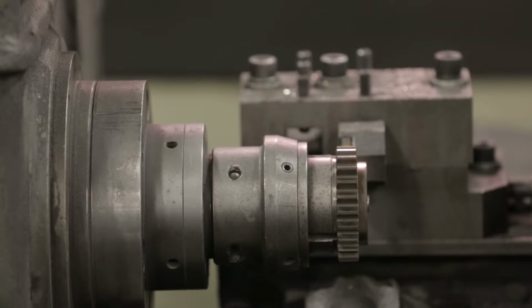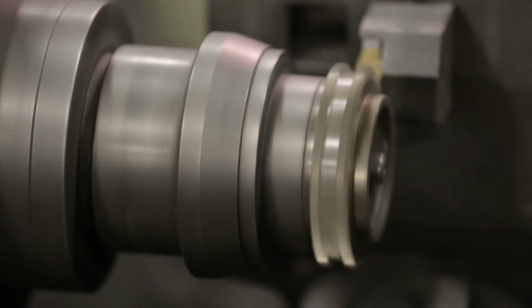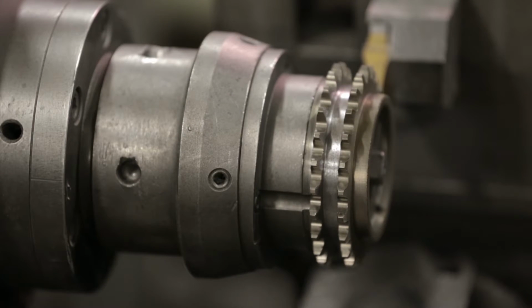We've gotten there. There will also be examples of, to save them cost, machining in the green state. That is advancing in stages now, where instead of just turning, you can do drilling, you can do many operations now in the green state. That's prior to sintering, so the tool life is exponentially increased. You may not gain a lot in terms of throughput, but you'll gain so much in tool life that you're able to offer a reduction in cost to the customer. And not only that, you make it a little easier to manufacture. You take out that variable, because every time you change a tool or an insert, you have the opportunity to change dimension, throw up a burr. There's always those offsets that need to be set.